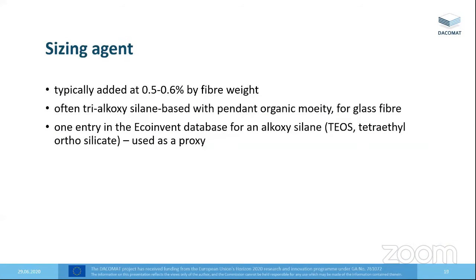We also add to composites, and this is a very important part of the composite from the point of view of damage tolerance, something called a sizing agent. And this is the thing that effectively bonds the fiber to the resin. The resin isn't necessarily going to bond very well to the glass fiber, so we have to have something in between, which is kind of an intermediate coupling agent. But if we look again, these are typically added at 0.5 to 0.6% by fiber weight. So the suspicion is already that there's not very much there. It probably doesn't matter.